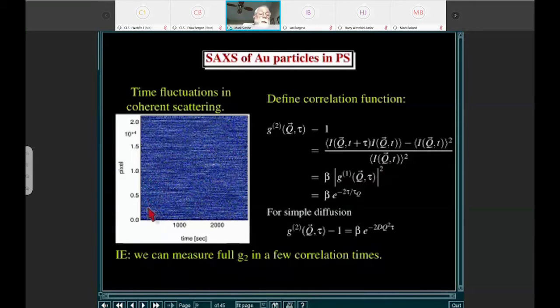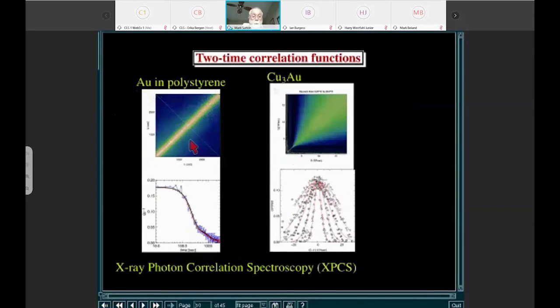So we can look at many, many speckles at a given time. In some sense, this is a spatial average. Then we can look at how the speckles correlate between two different times. We can take T1, where we have over 20,000 speckles, and another time T2, with another 20,000 speckles. We can calculate the intensity correlation function, and what we measure is what we call a two-time correlation function. In the left-hand plot here, where we are looking at the gold particles in the polystyrene, which is the data I was just showing you, if the two times are very close together, the correlation is always very high. If the two times are far away from each other, the correlation is very low, and that's what's plotted on this color plot.